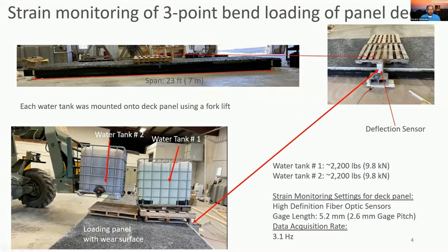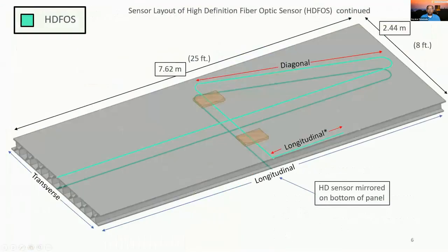We used whatever we could. This happened to be the high bay area of Morgan County Highway Department. And you could see that the riding surface, which has a co-cure material system with the vinyl ester based composite at the base and a riding surface with stone integrated in it. And so it is very critical to make sure that this riding surface doesn't shear off. So a lot of this development was detailed as a part of the project.